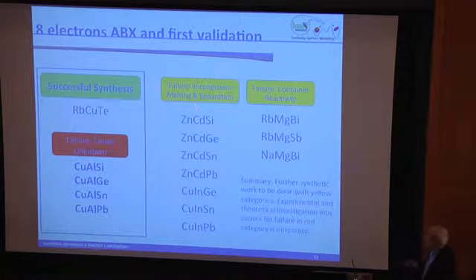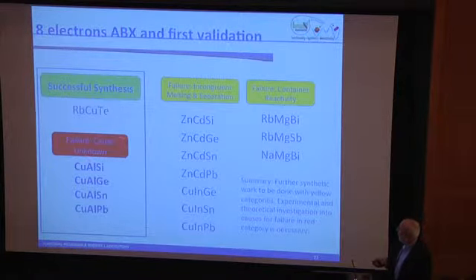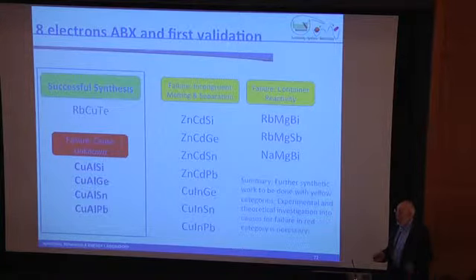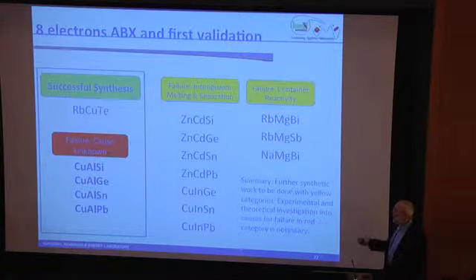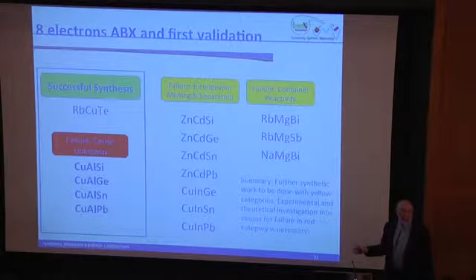But as I said, it's very non-trivial to be able to get these from the synthesis, because it tells you it's thermodynamically stable. It does not tell you what the synthesis route into it is. So, you know, we successfully synthesized the rubidium copper telluride. These all failed because they have incongruent melting. These failed because they all reacted with the container. And these failed because we don't know. But as we get a better understanding of the synthesis, we hopefully can go back and put that in, and then we'll know which ones we might be able to get to by which route.